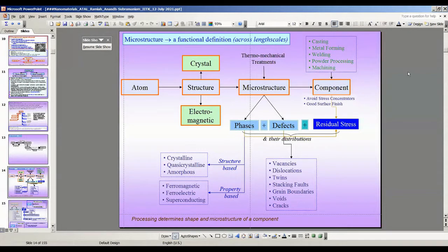So the answer to that question is that there is no such number I can give, because it depends on the microstructure. Is the microstructure martensite, tempered martensite, pearlite? That will determine the yield strength or the hardness. Okay. Now,